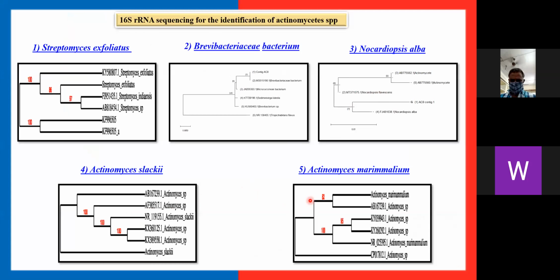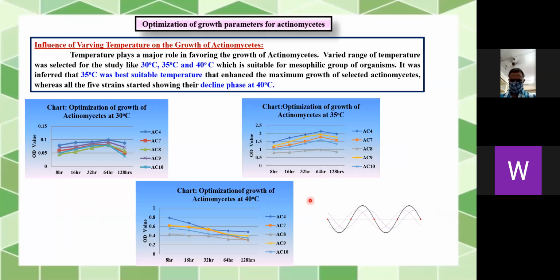Optimization of growth parameters: influence of varying temperature on the growth of actinomyces. Temperature plays a major role in favoring the growth of actinomyces, and a varied range of temperature was selected for the study, out of which 35 degrees centigrade was the most suitable temperature that enhanced the maximum growth of the selected actinomyces, whereas all 5 strains show their decline phase at 40 degrees centigrade.